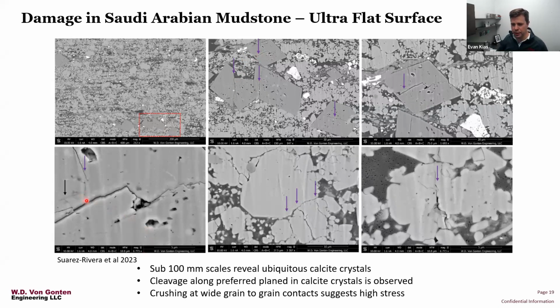Taking a closer look, you see complicated behavior associated with shear stress, and at grain contacts, especially large grain contacts, we see a lot of crushing. Typically a point contact creates a large stress concentration, whereas a long contact distributes that stress more efficiently. Seeing the crushing at those distributed boundaries is strong evidence of the amount of stress in the sample.